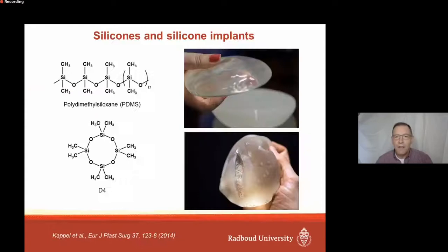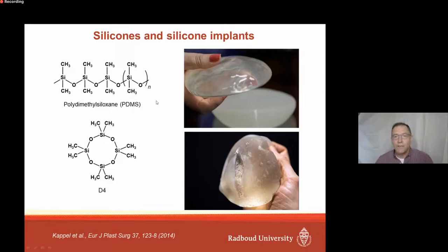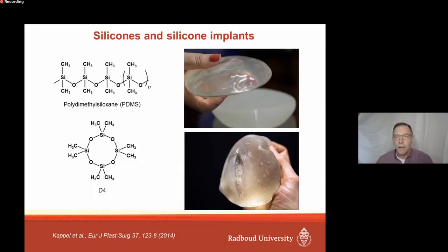It will be quite well known to you that silicone breast implants are filled with silicone gels. The main component of silicone gels is poly dimethyl siloxane - PDMS in short - which is also cross-linked in order to form the gel-like structure. During the process of production of these gels, there are also a number of low molecular weight silicones generated, like the most prominent compound, the so-called D4 silicone, which is a cyclic silicone consisting of four units of siloxane.